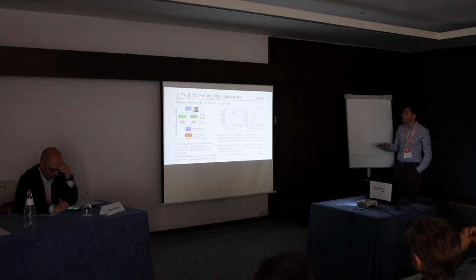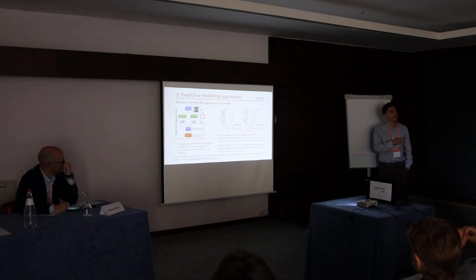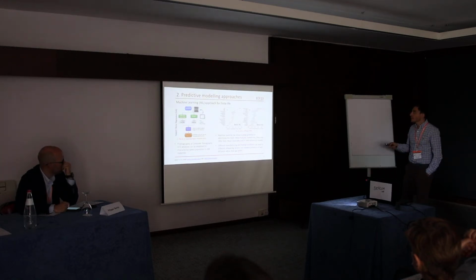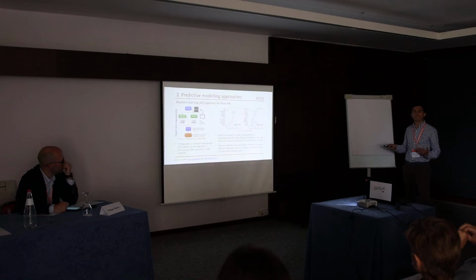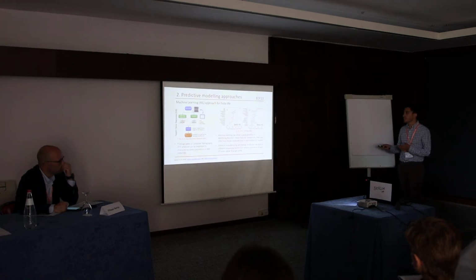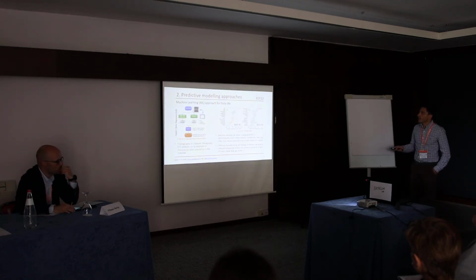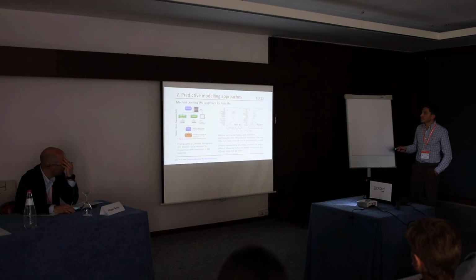And we can see that if we consider 2 different batches, manufactured with 2 different manufacturing processes, the influence of each feature is different, right? So in one case, for example, I was talking before about the distance from the surface of each defect. Here in batch 1, the influence is very low. In batch 2, it is very high. So how is that possible?